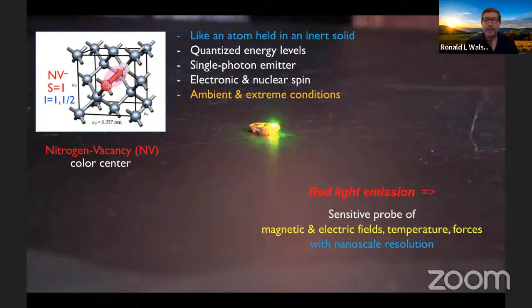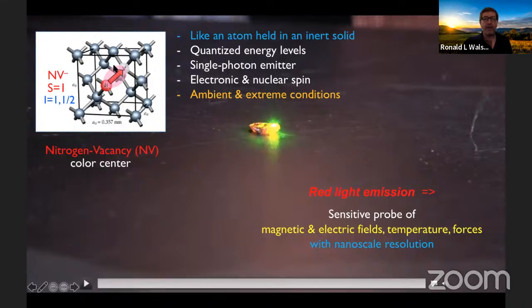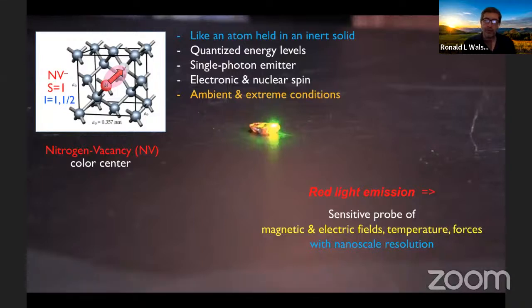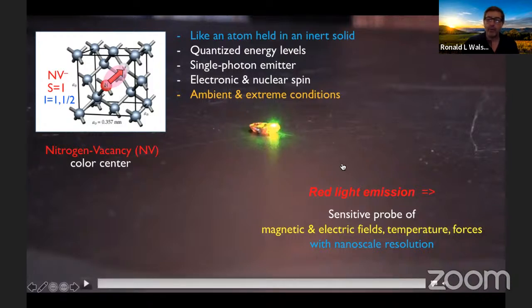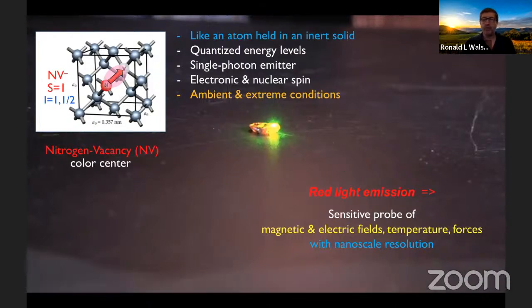As I mentioned before, NVs tend to absorb green light and emit red light. And the red light emission and the rate of fluorescence that the NVs are giving off in the presence of green light illumination, that's the measurable. That is the thing that the experiments are always measuring or imaging. So the intensity of the red light per NV gives you information about its environment, like the local magnetic and electric fields, the temperature it's exposed to, et cetera. And because the NV is literally atomic scale, an individual NV will give you information about these things right around its neighboring location at this angstrom scale. So you really can get nanoscale spatial resolution in certain conditions.